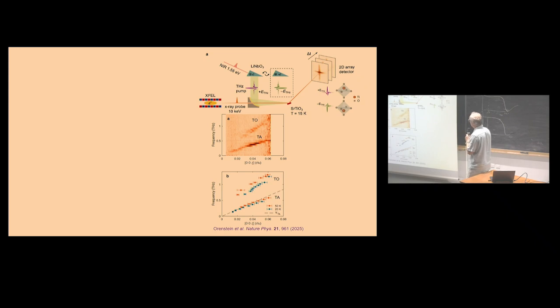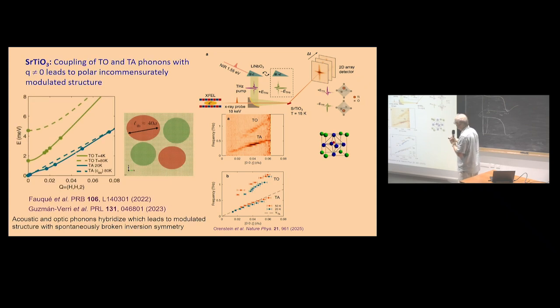And they observed that there is some coupling of the optical branch with the acoustic branch at non-zero Q vector. And here are even calculations. And this coupling of optical and acoustic branch produces a gradient of strain, and therefore there should be some polar nanoclusters. Shown here, yeah, the clusters are a nanometer or 40 atomic unit cells, and so you have softening of the phonon, which is responsible for the increase of permittivity at low temperature, and then some coupling at non-zero Q vector producing such strain.